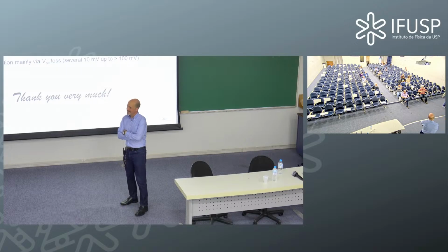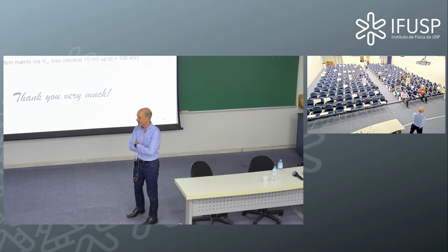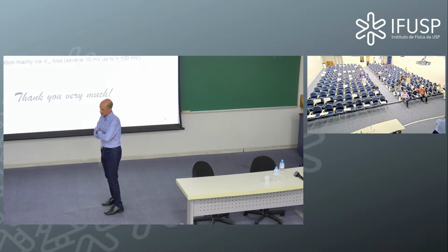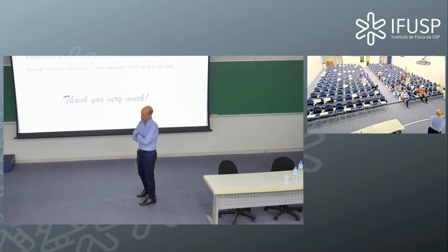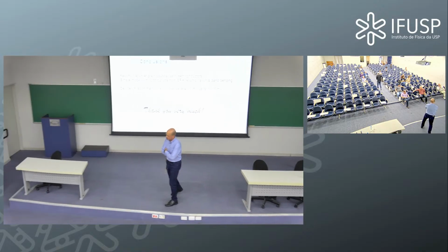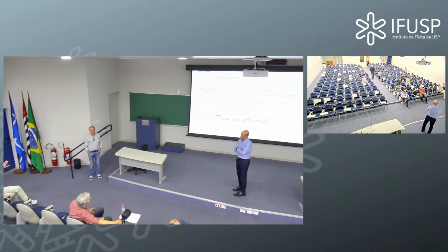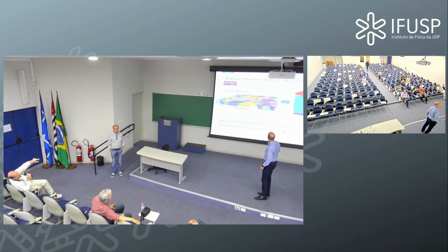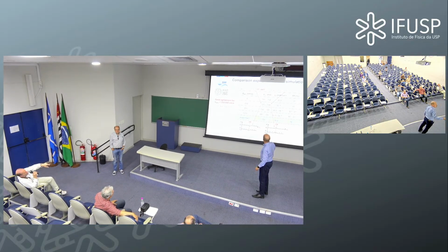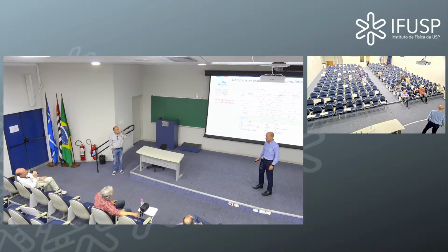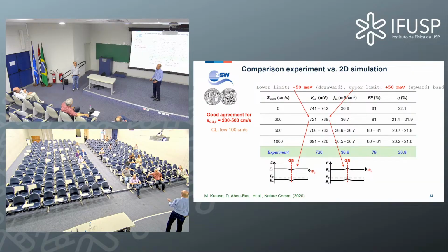Hi, Daniel. These solar cells you showed us, these are the CIGS solar cells, right? Yes, CIGS. The fill factor and the current are okay, but your VOC is quite low. Is it typical of this kind of solar cell? Yes, even for silicon, it's not so large. Because the bandgap energy is low, it's 1.1, 1.15, and so at the Shockley-Queisser limit, it would be 900 millivolts.